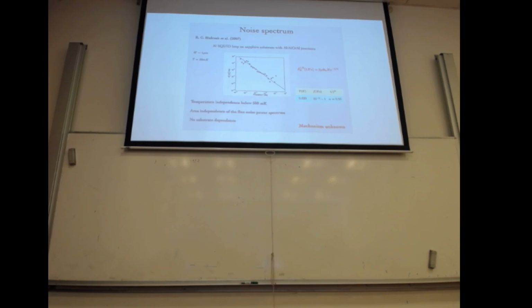Until people started to work on qubits, and then they realized that this noise comes back, and it's the same noise. So these are recent measurements that were done in 2007 in the lab of Martinis. What you see is that they were using an aluminum SQUID loop on a sapphire substrate with aluminum junctions, and the width of the SQUID was on the order of a micrometer. They were going to very low temperature, 20 millikelvin, and basically what they were showing is that there is 1/f flux noise,